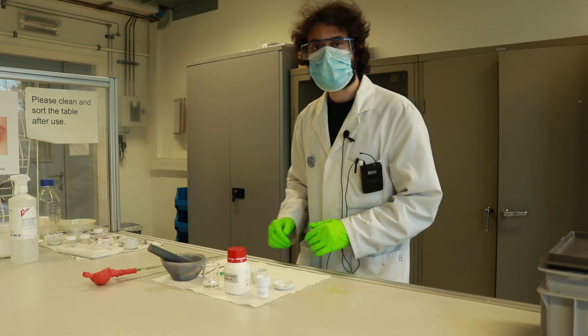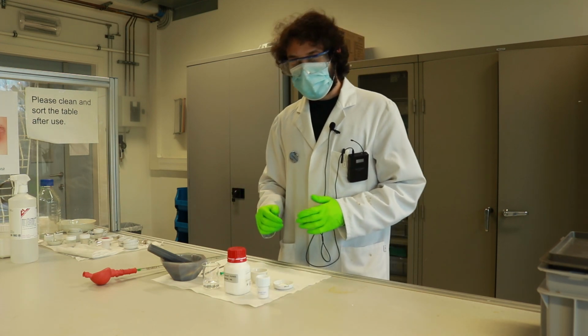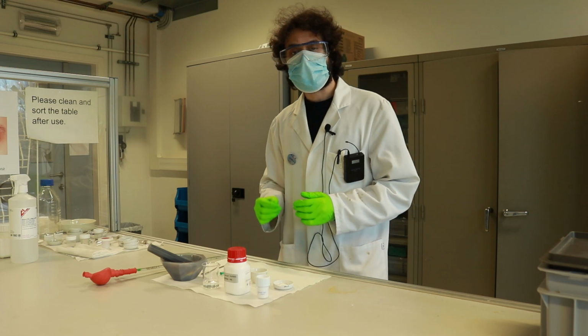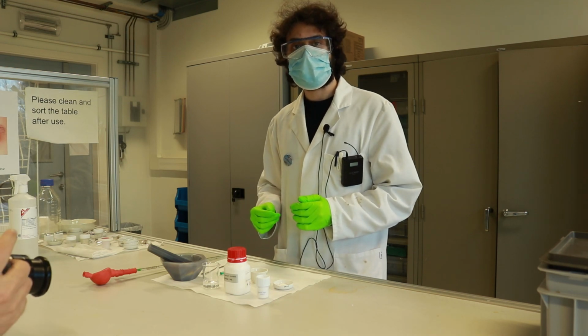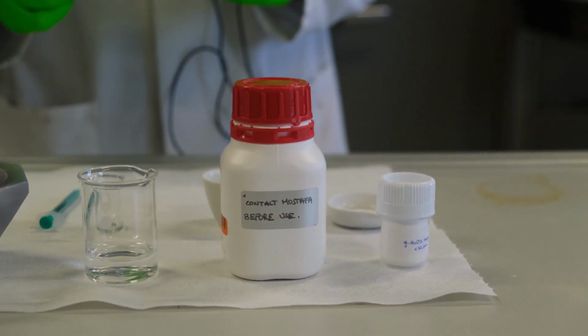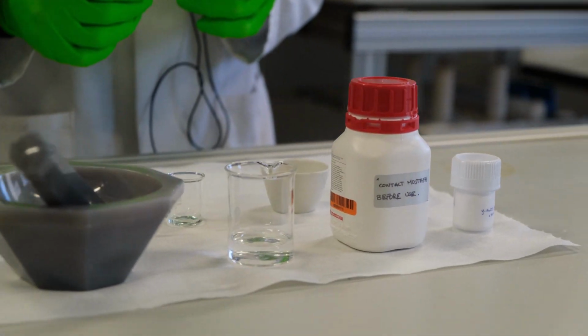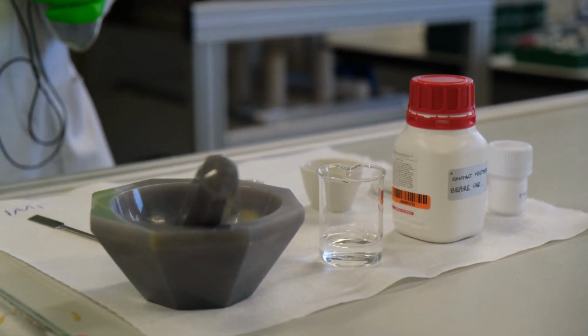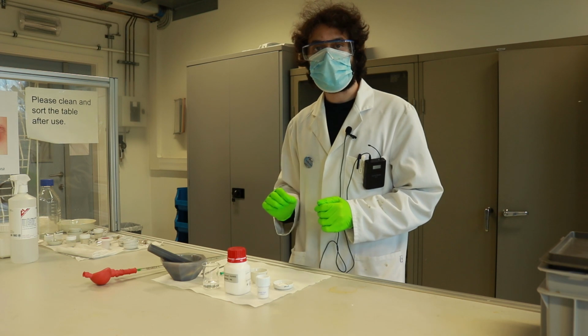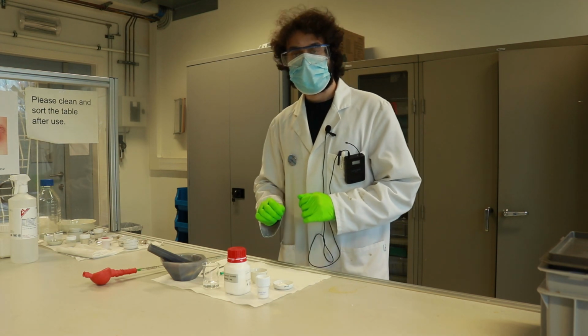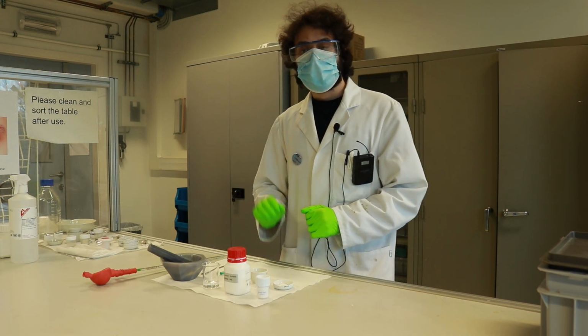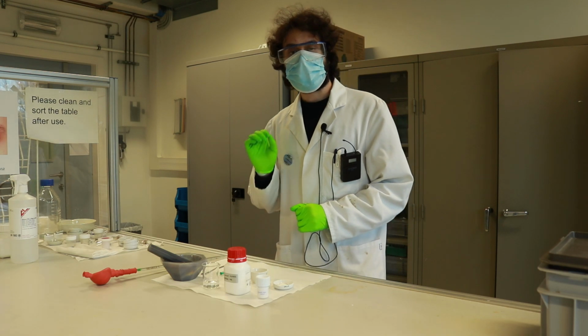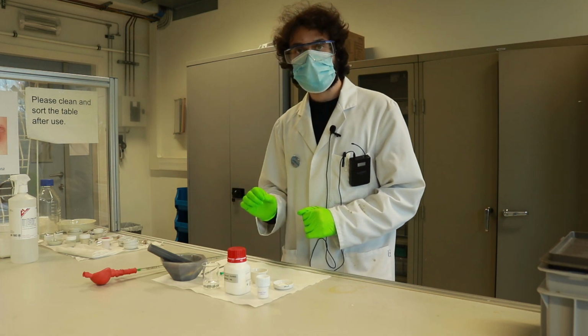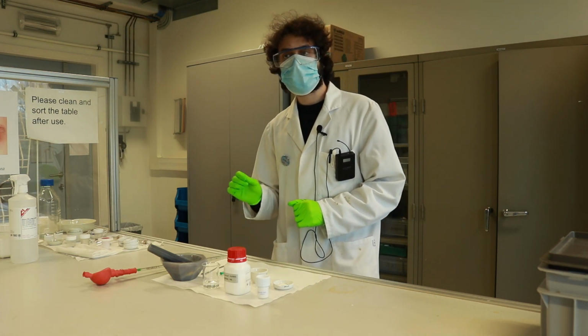The incipient wetness impregnation requires us to use a solution that contains the active metal to fill up the pores of this carrier. And so, in order to have proper dry or incipient wetness impregnation, you must match the pore volume of the sample to the amount of solution that will be added.